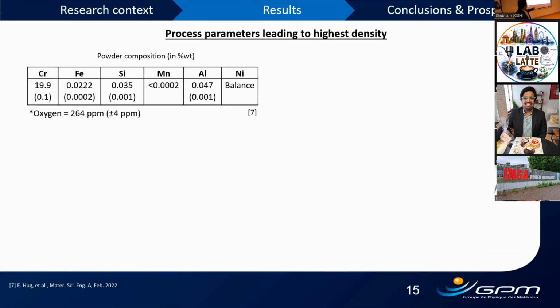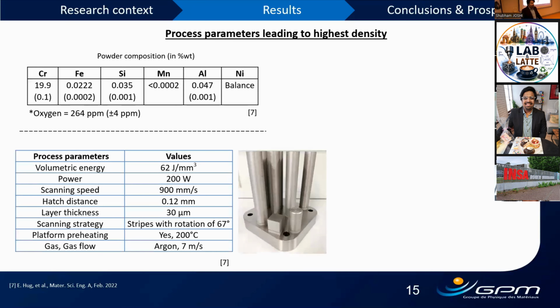Before going for initial microstructure, it is important to understand how the powder was acquired. So we acquired the powder commercially, and the powder composition in weight percentage can be seen here. 20% chromium was desired, and we have 19.9. Unfortunately, we have some trace elements: iron, silicon, manganese, and aluminium, but the weight percentages are quite small, and the balance is nickel.